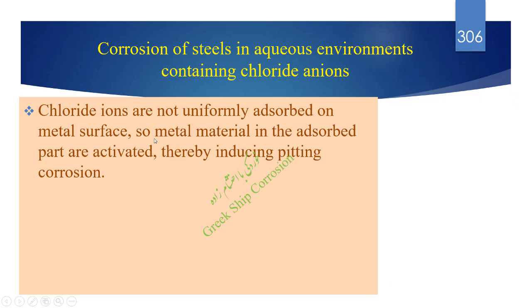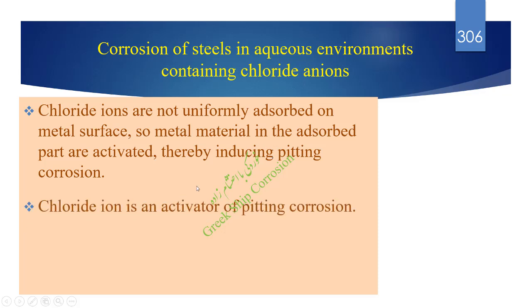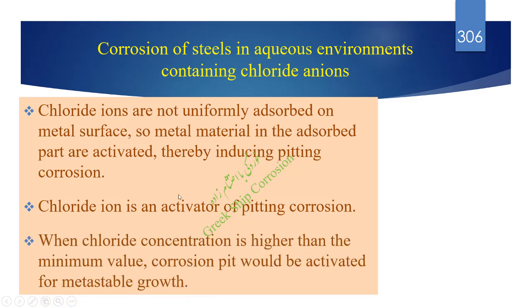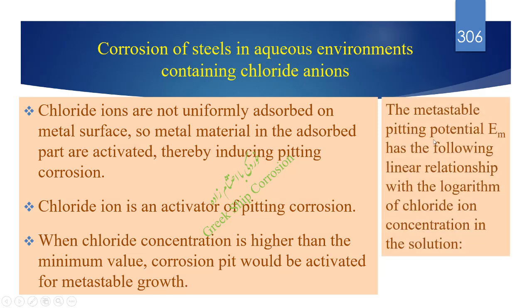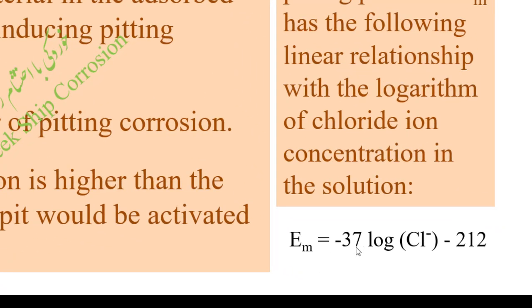Chloride ions are not uniformly adsorbed on the metal surface, so the metal material in the adsorbed part is activated, thereby inducing pitting corrosion. Chloride ion is an activator of pitting corrosion. When chloride concentration is higher than the minimum value, the corrosion pit would be activated for metastable growth. The metastable pitting potential EM has the following linear relationship with the logarithm of chloride ion concentration in the solution. EM equals minus 37 log of chloride ion concentration minus 212.